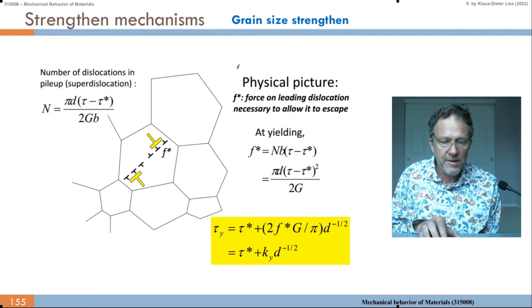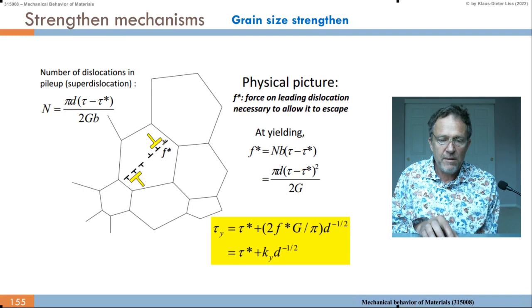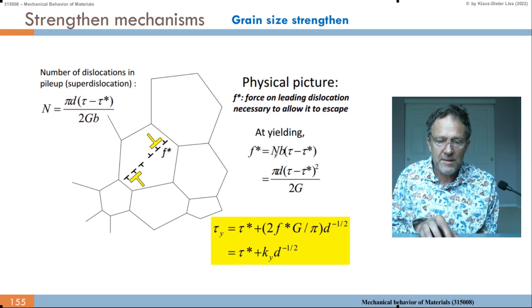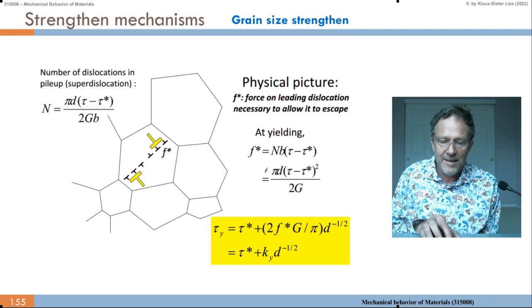So the grain size strengthening is shown here again. Physical picture. We get a force F star. So the force F star is n times the Burgers vector. So n dislocations push on each other. Here 3 of them push each other towards the wall, times the shear stress, or the exceeding shear stress above the natural intrinsic stress, and that becomes then pi d over 2g. And from this force we can estimate the number of dislocations in the pile up of the super dislocation: pi times d times tau minus tau star, the exceeding stress over the intrinsic stress, divided by 2gb.